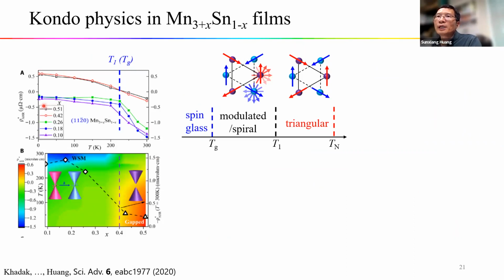Now we look in a little more detail at the DC Hall effect as a function of temperature for different compositions. For the low doped sample, we have a large negative normal Hall at room temperature. It decreases, and it seems that there is a phase transition around 225 Kelvin. Below that temperature, this normal Hall decreases slightly as temperature decreases. For the highly doped one, the negative normal Hall is much smaller, roughly one order smaller than the low doped one, and it changes sign along this temperature. Below that, we have the positive normal Hall, which increases with temperature.